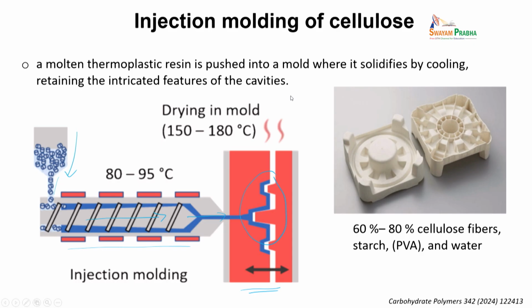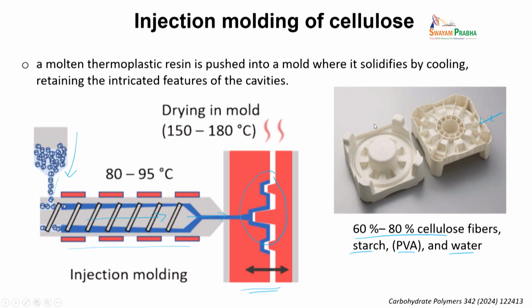So what has been possible with cellulose is that you cannot use pure cellulose in this process. Okay, it doesn't work that way, but a lot of work has been done where they mix cellulose with other material. In other words, cellulose is used as an additive in other matrix polymers. Okay, so here is one example. You can see it's a very intricate design, printed or maybe injection molded, but this material consists of about 60 to 80% cellulose fiber. It has starch, PVA and water, right? So there is much work where cellulose is mixed with other polymer, just like this case, and then you optimize the temperature and then mold into this. So, injection molding of cellulose is also an emerging application.